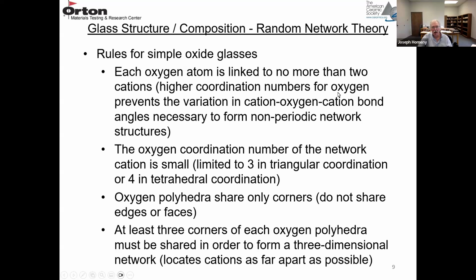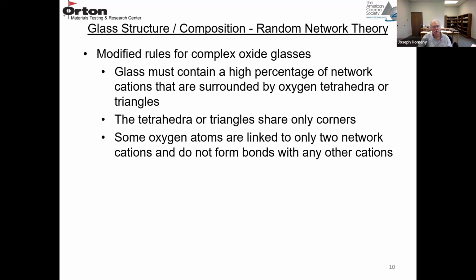So the higher coordination numbers for oxygen prevents the variation in cation-oxygen-cation bond angles necessary to form a non-periodic network. So each oxygen atom cannot be linked to more than two cations. So the oxygen coordination number of the network cation is small. It's 3 in a triangular coordination or 4 in a tetrahedral coordination. Then these oxygen polyhedra, whether triangular or tetrahedral, can only share corners. They don't share edges or faces. And at least 3 corners of each oxygen polyhedra must be shared in order to form a 3-dimensional network. So this type of sharing of corners locates cations as far apart as possible. So that's for a simple oxide glass.